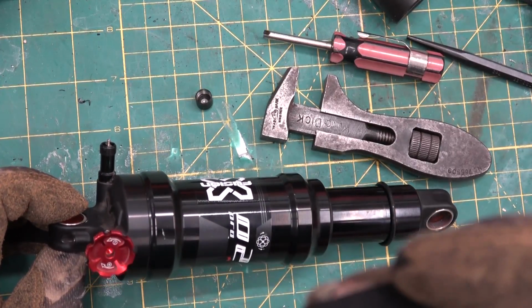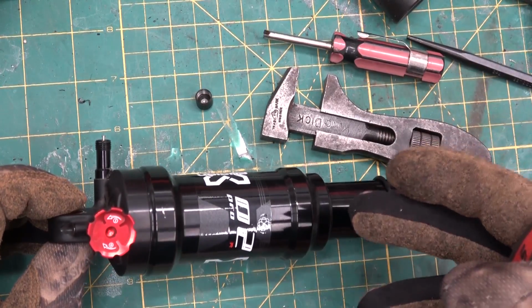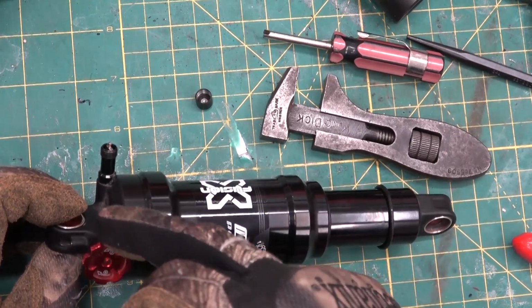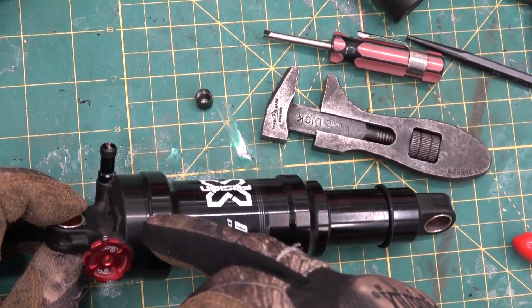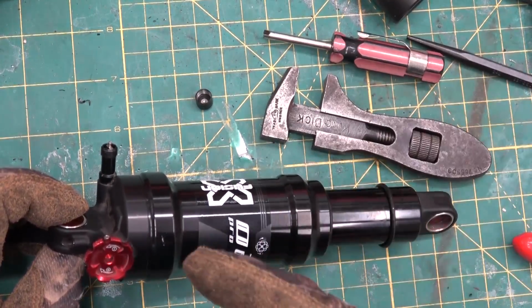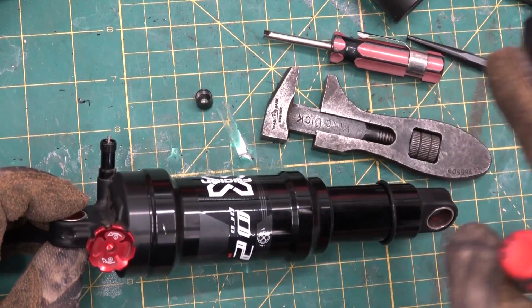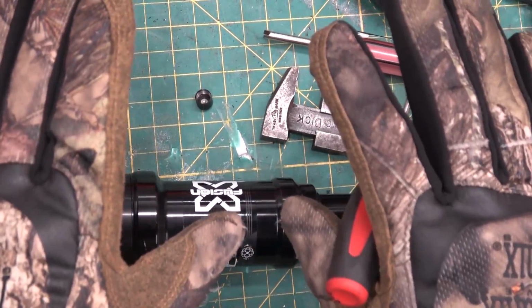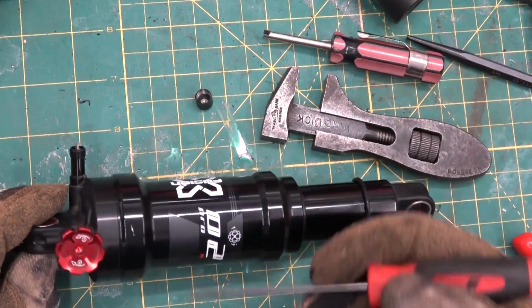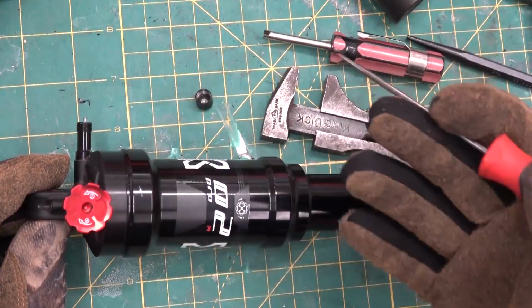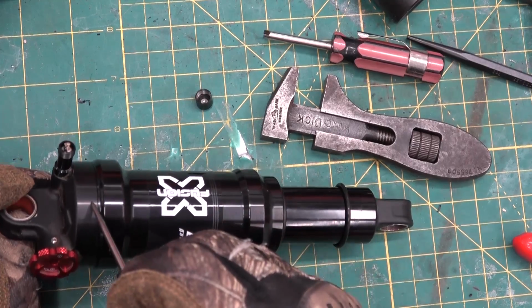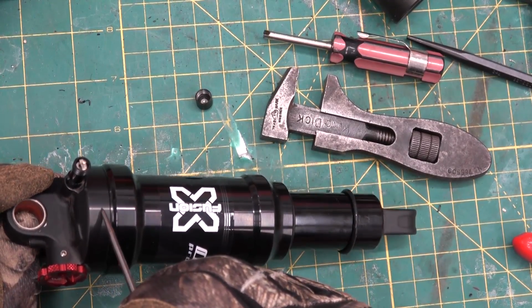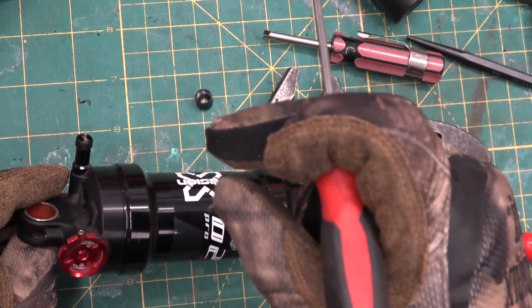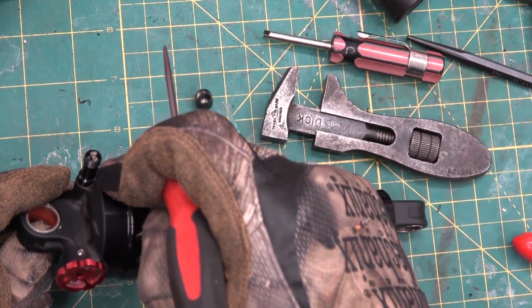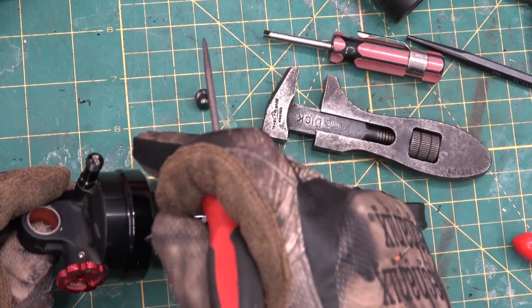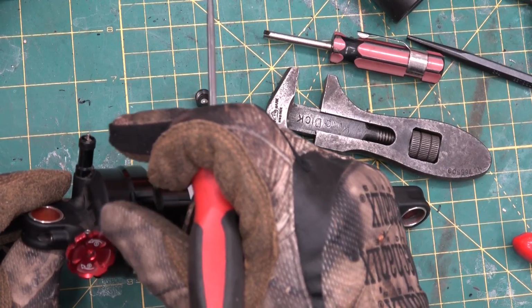Now, when you anodize these, what you're doing is you're passing direct current through the workpiece, through the anode, cathode. They change depending on if it's a battery, I always get mixed up. It's like my right-left dyslexia. I don't know if it's my left or your left. So in this case, very likely it would be a type 2 anodizing, which means that it's forming pores in the material, and it's also thickening that oxide layer.